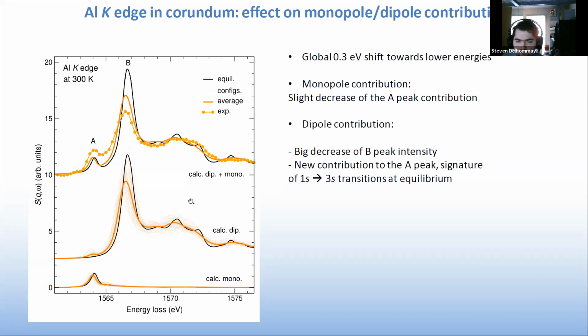So we can just for now make simple observations, I would say. First, we can notice that there is a slight shift towards lower energy when we use the protocol, of about 0.3 eV. The second thing to notice is that there is a much bigger effect of those vibrations on the dipole contribution. Here we can see that the configurations are very dispersed. It's not the right word, but you get the idea. Compared to the monopole, where the configurations are still quite stacked. So bigger effect on dipole contribution than on monopole contribution.